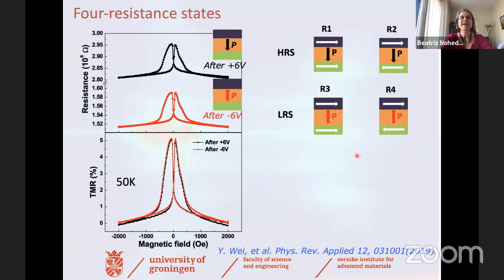If now we use the fact that our tunnel barrier is a ferroelectric, we can actually switch the polarization of the ferroelectric, and we apply here 6 volts to switch the polarization down and minus 6 volts to switch the polarization up. And these differences in polarization are known to also bring differences in the average barrier height. And that's a well-known effect. And that is bringing differences in resistance of the tunnel junction. And you can see then that by these two effects, the TMR and this tunneling electroresistance effect of the ferroelectric switching, we can have four resistance states in our tunnel barrier, which is already a very nice result.